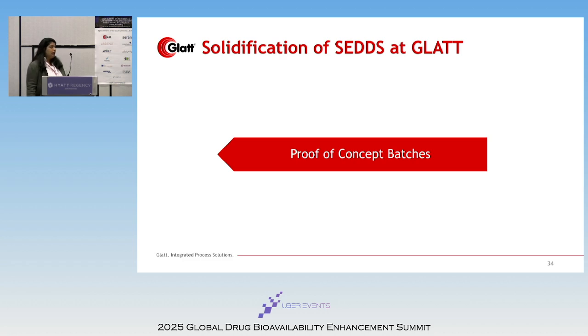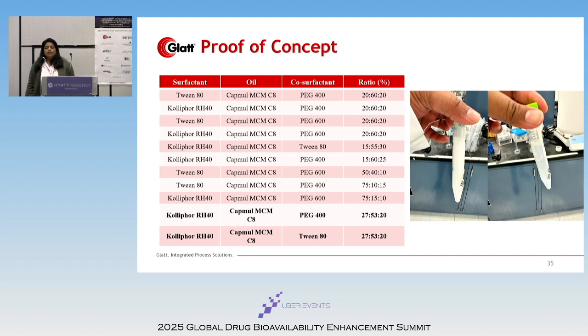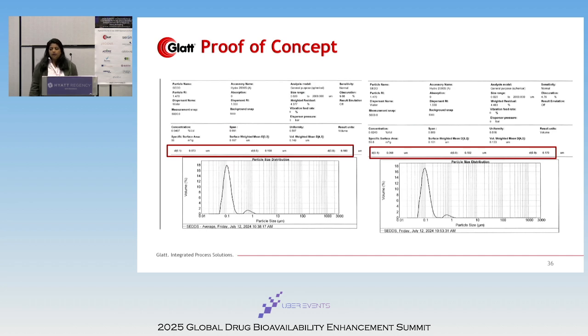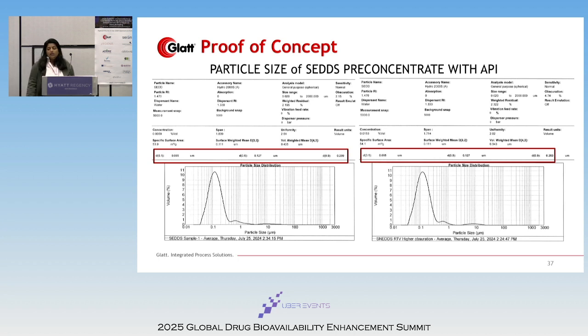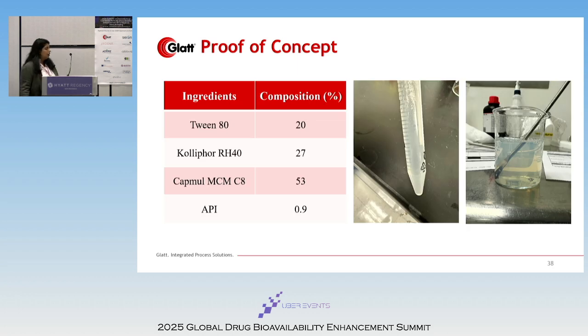So we planned to do a proof of concept here. Our proof of concept first was to understand what kind of formulation we were looking for when we were talking about SEDS. Like always, for the ternary graph, you have to do certain pre-formulation work, right? So we went through certain surfactants and co-surfactants, saw the ratios, and we were able to find a SEDS formulation that gave us the particle size that we were looking for. We looked at around 100 nanometers, and we got around 107, 106 nanometers, and we went ahead and incorporated a drug into it. When we incorporated a drug, we did see an increase of the particle size, which was known for us anyways. So we were still within the range that we were looking for, so we went ahead and did our first batch of proof of concept.